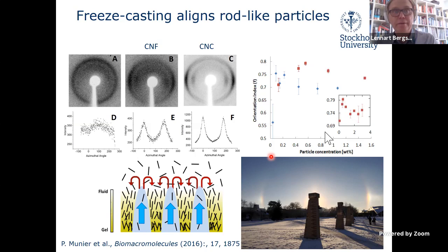Freeze drying and freeze casting has the possibility to align the fibrils, meaning you have a possibility to utilize the anisotropic properties of the fibrils, because as I said before, there's a factor of 8 difference in thermal conductivity in the axial and the radial direction.